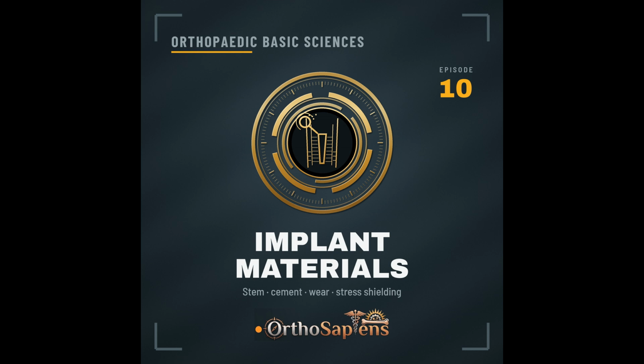in the operating room. And what level of vacuum is required to actually pull those bubbles out of a thick, gooey cement? The standard requirement is roughly an 85% vacuum. 85%. I'm going to repeat that number twice because it's specific and important for the exams. Vacuum mixing at roughly 85% vacuum is the most significant way to reduce porosity in cement. Again, you need an 85% vacuum to effectively suck the air out and prevent crack starters.